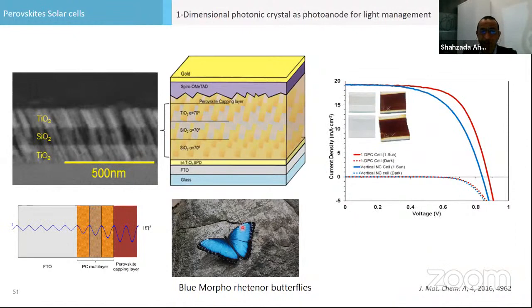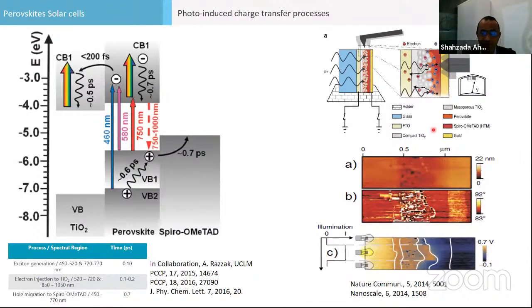Similar things we studied: we modulated titanium dioxide and silicon dioxide, because the refractive indices of these two materials are very different. TiO2 is 2.4, SiO2 is 1.45. By doing so, we can also modulate this type of light management concept, which has been used in silicon. Now we need to emphasize more on this type of thing for better solar cell fabrication, and this also improves our performance.